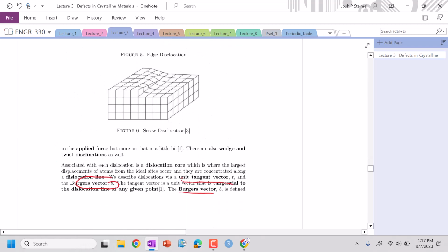What about screws? Screws are a little bit harder. Again, I see the defect here. It is penetrating in through the crystal, so I can go down or up. I'm going to choose my tangent vector as going up here. Now, here's the tip for your starting point. I want to start right at the edge of this defect, but I can choose here or here.